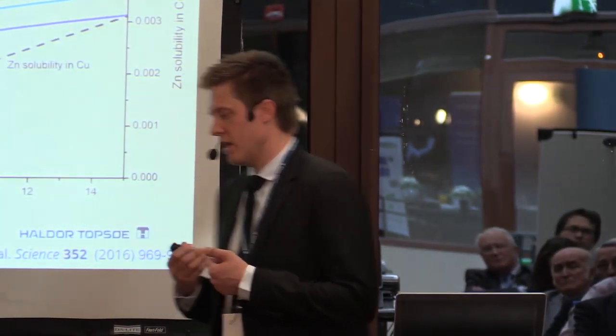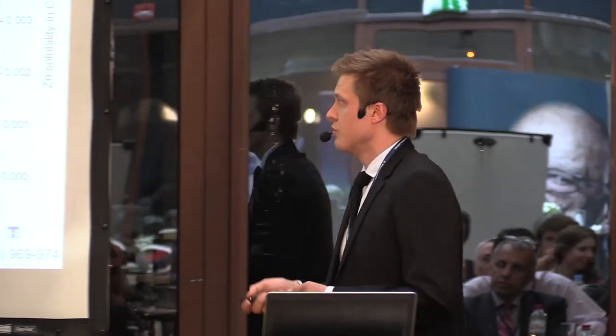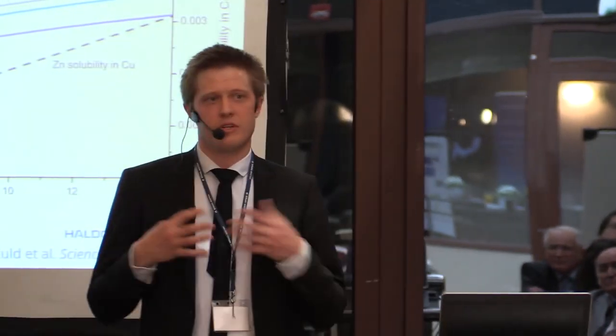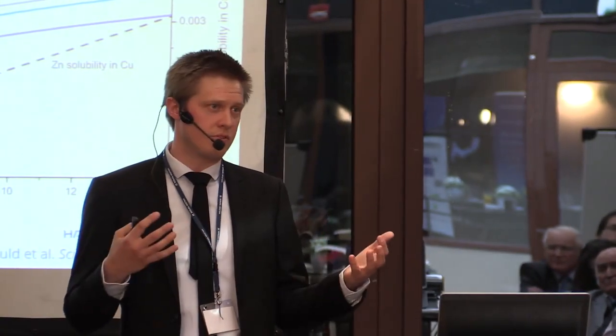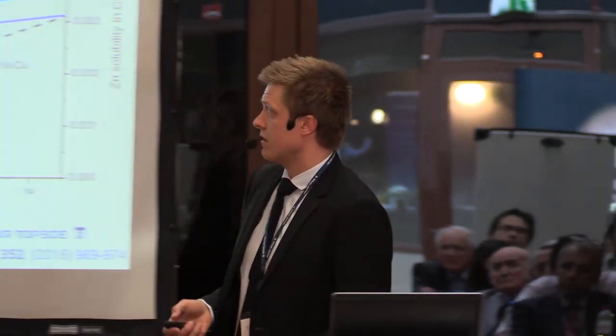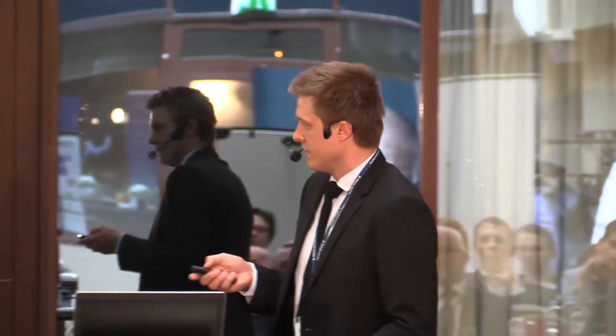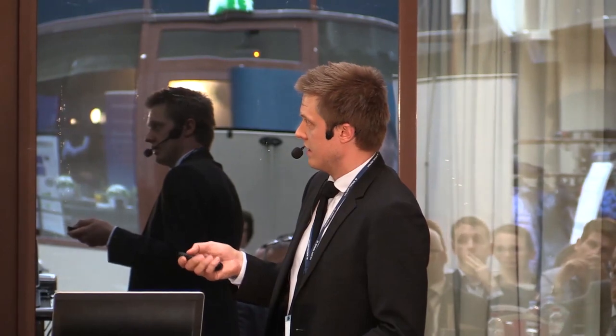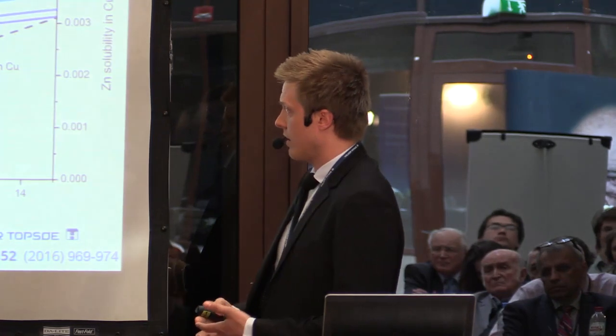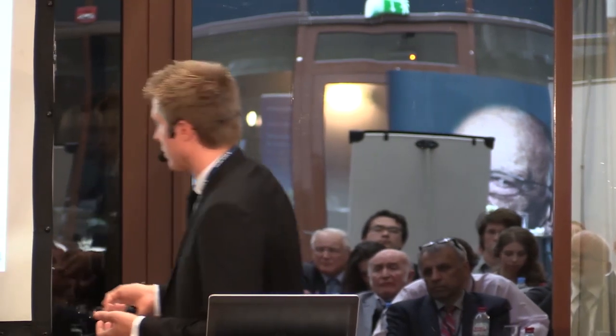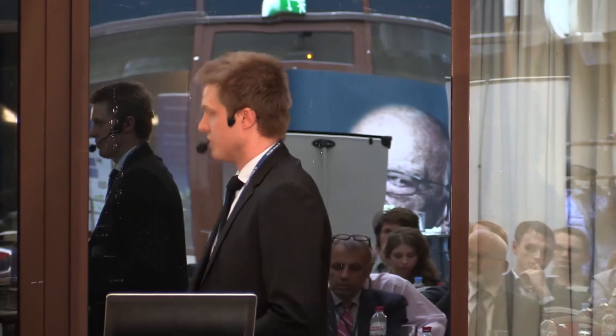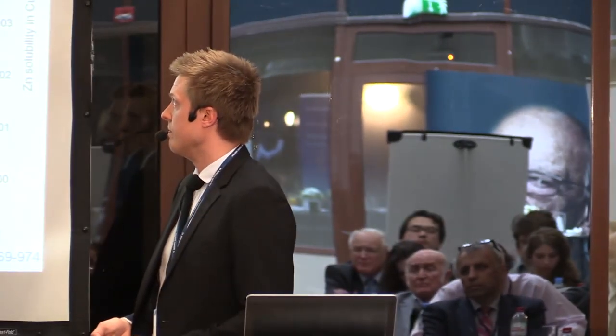But of course, we need to model a real nanoparticle. So we took this idealized shape of a cuboctahedron, which has a very distinct ratio between all these types of surface sites. So we can really calculate how it would look on such a nanoparticle, and it's only slightly higher than the copper 111 surface. So now we actually have a model where we can model how much zinc you will have in the surface of your copper particles as a function of the reduction potential of your synthesis gas, or the CO-CO2 ratio.